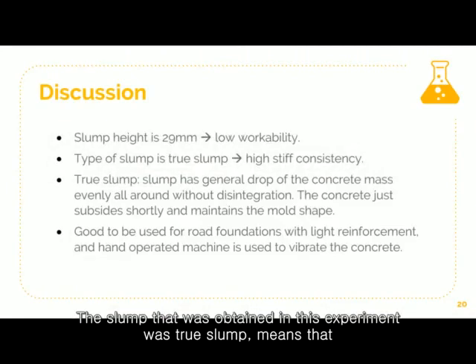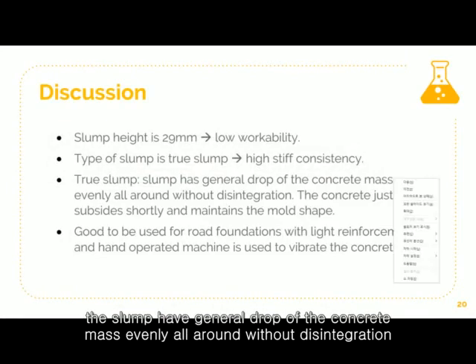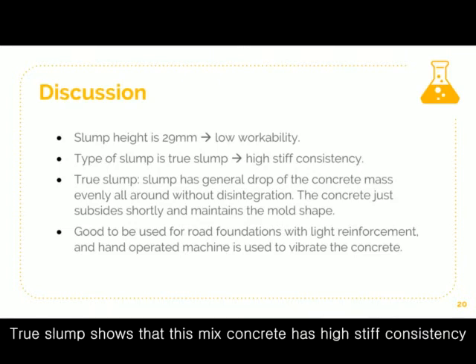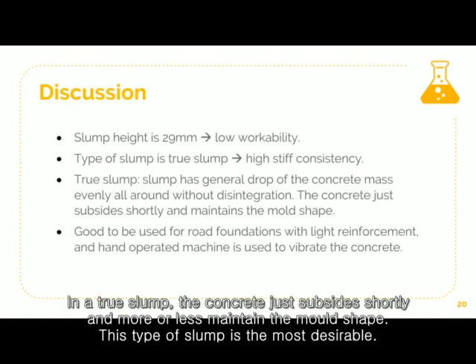The slump that was obtained in this experiment was true slump, which means that the concrete mass drops evenly all around without disintegration. True slump shows that this mixed concrete has a high stiff consistency. In a true slump, the concrete just subsides shortly and more or less maintains the mold shape. This type of slump is the most desirable.